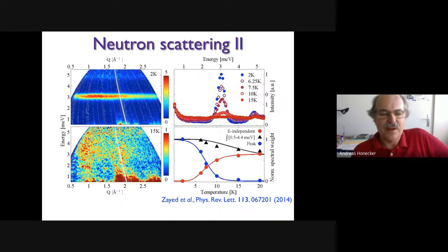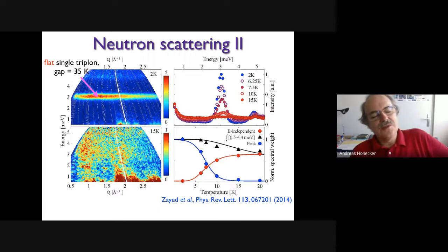Okay, now here's another version of the same thing, and that is actually the experiment that motivated the work that I'm going to present in the rest of this talk. So this is 2014. It's a few years old, but things go a bit slowly in that field. So again, you see here in the upper left panel a flat dispersion relation at 2 Kelvin. And again, this is a fingerprint of strong geometric frustration, and the energy of 3 milli-electron volt corresponds to the excitation energy of 35 Kelvin.